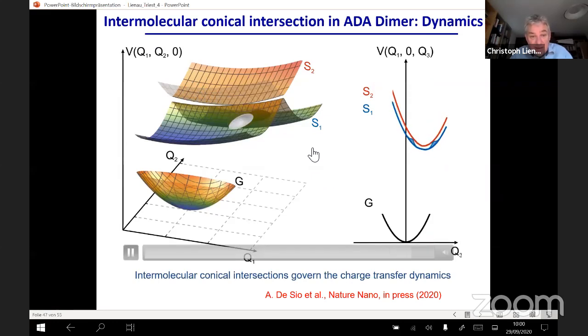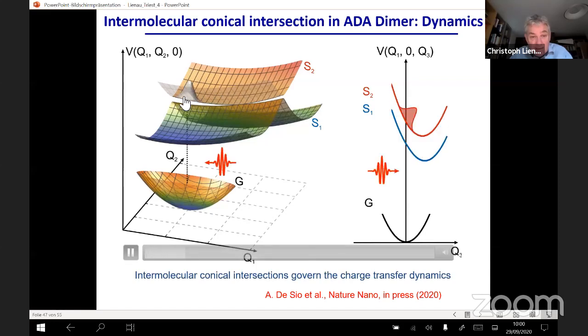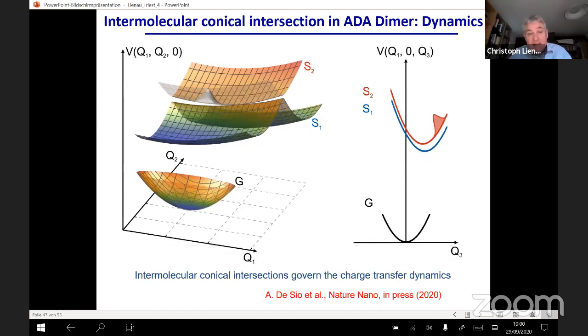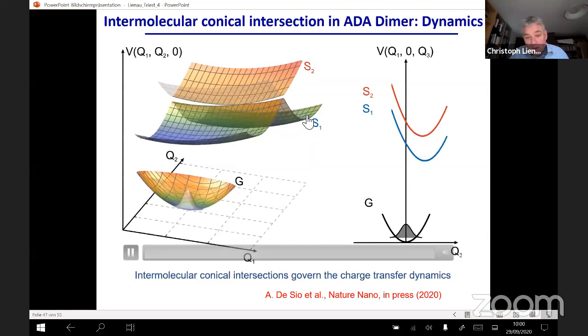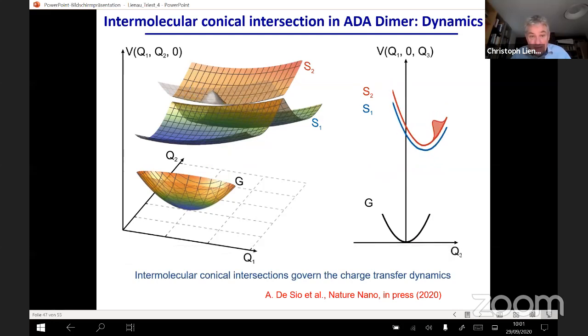You can capture this in the form of a small movie. Here we have sketched the conical intersection surface. There's also a third coordinate along which the system vibrates. Here we have followed how such a wave packet in a dimer is generated on an optically bright electronic state of the dimer, moves towards the conical intersection within 40 femtoseconds, and then by means of electron-vibrational coupling, jumps reflectionless to the optically dark S1 state of this dimer, where it then localizes into excitons. And you have seen that the trick that we have played to analyze this process is again to use ultrafast coherent spectroscopy, in this case, in particular, 2D electronic spectroscopy.